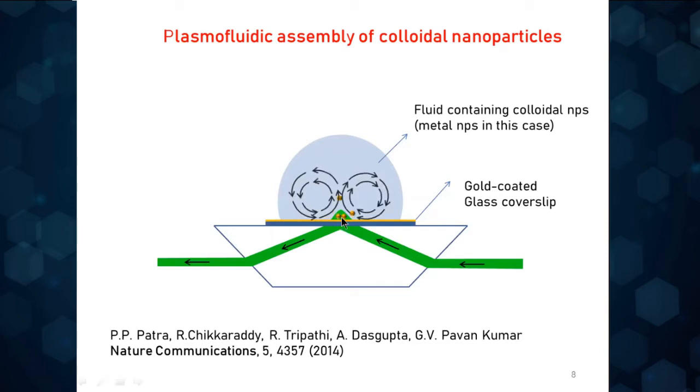and that absorption leads to heat, and that heat creates a gradient of temperature, and the gradient in temperature creates a convection field, and this field sets the fluid in motion. As a function of time, you start seeing assembly of these colloidal particles at the location of interest. What is interesting is that you are utilizing the optical field, converting that into a thermal field, and this thermal field sets up a mechanical field, and that mechanical field further leads to some very interesting assembly processes. So we are interested in assembling colloidal particles using such an optical field.